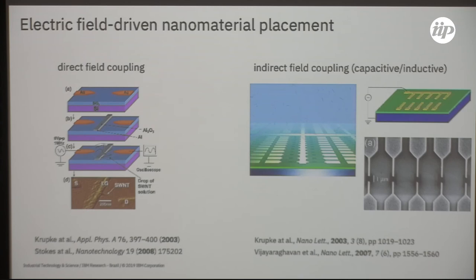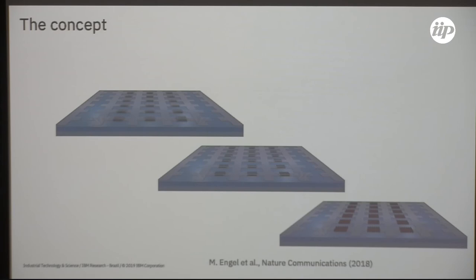We thought: why not use graphene electrodes to do the same thing? We have experience that metallic electrodes used for assembly can deteriorate device performance — in high-frequency studies on those transistors the metal lines typically deteriorate the performance. It would be good to remove the deposition electrodes, but metal electrodes are very hard to get rid of. Graphene would be nice — it's the ideally flat two-dimensional deposition electrode and it could be removed with a very gentle etching step.